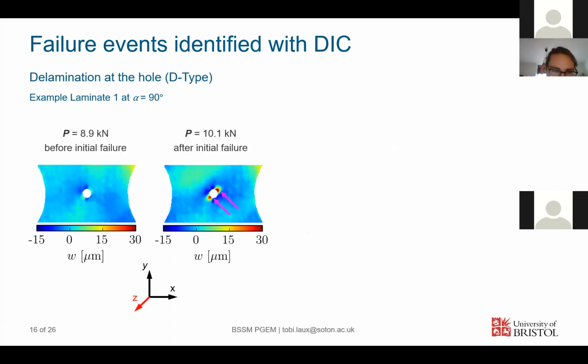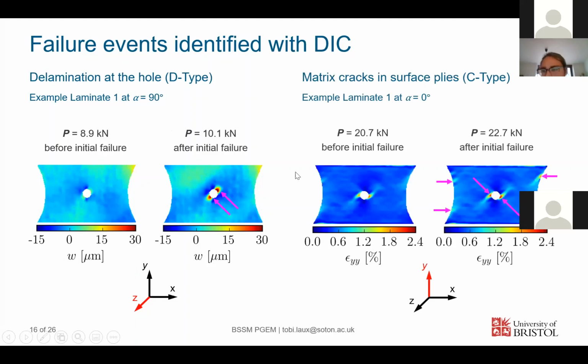things we got from our DIC maps. With DIC, amongst other things, we identified some damage types. Looking at the out of plane displacements, for example, we managed to correlate local out of plane displacement gradients, which suddenly happen at a certain load, with subsurface damage. And a second type of failure which we were able to observe is matrix cracking in the surface plies.